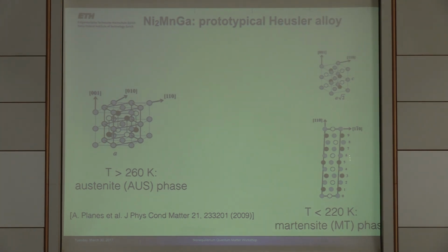But another thing that characterizes it that's actually very important for the magnetic shape memory effect is essentially a twinning superlattice formation that pops up. This is one example of it. It depends on exactly what the stoichiometry of the material is. This is the one for what I've drawn here. Basically, you have this thing that looks like a periodic superlattice modulation at low temperatures.